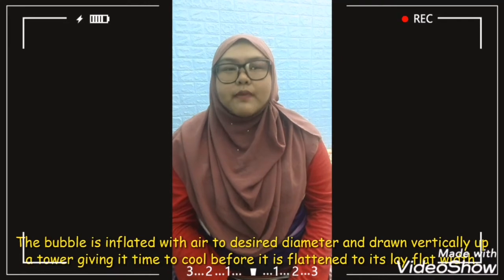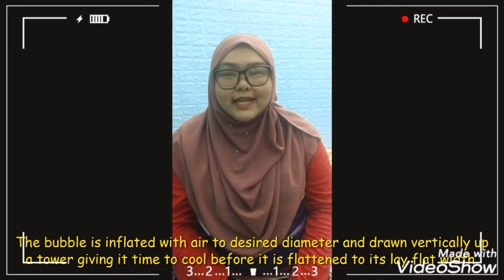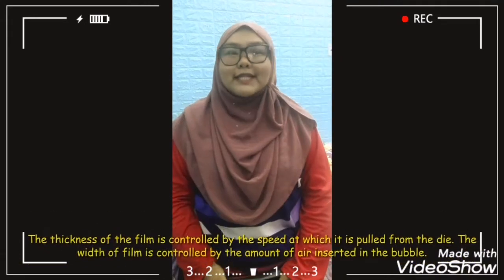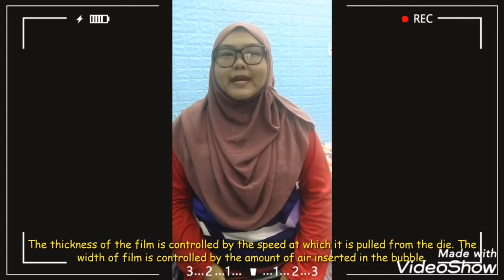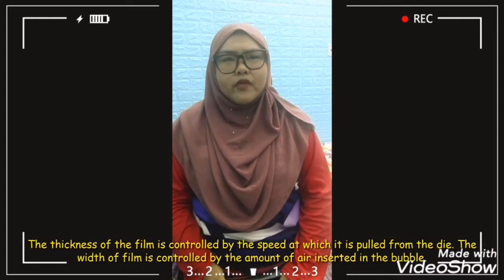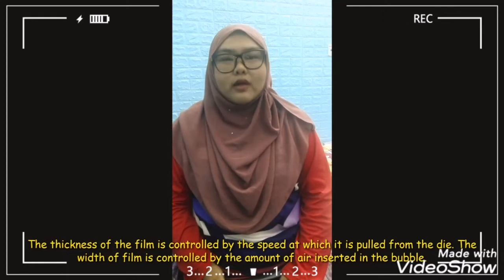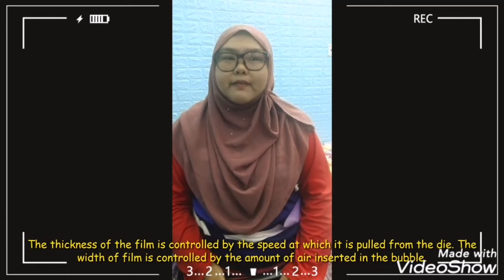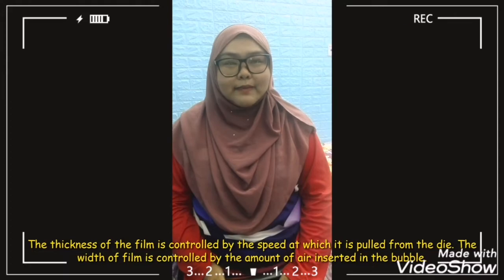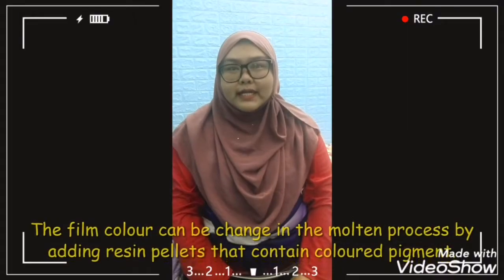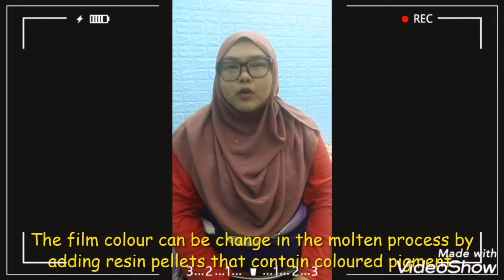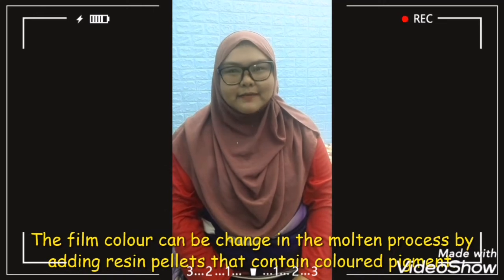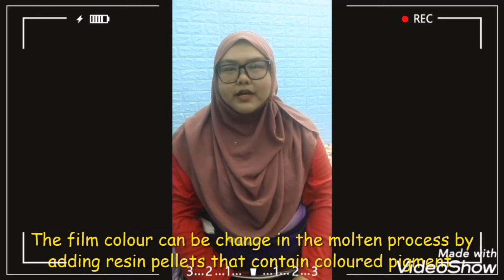The bubble is inflated with air to the desired diameter and drawn vertically up a tower, giving it time to cool before it is flattened to its lay flat width. The thickness of the film is controlled by the speed at which it is pulled from the die. The width of the film is controlled by the amount of air inserted in the bubble. Film color can be changed in the molten process by adding resin pellets that contain color pigment.